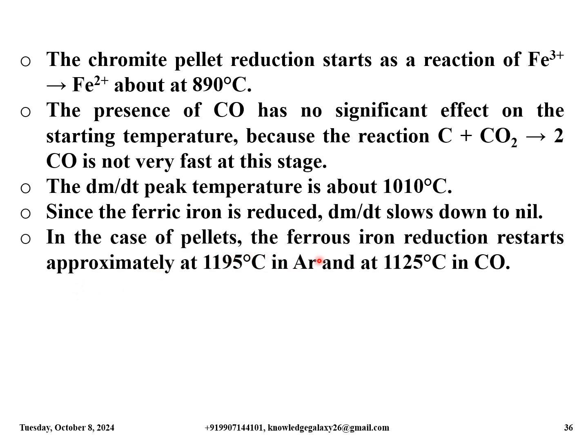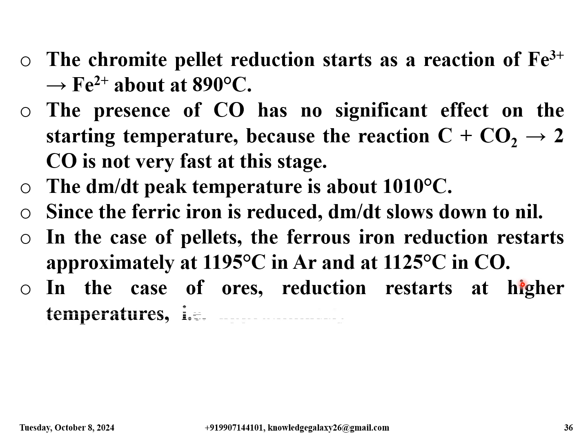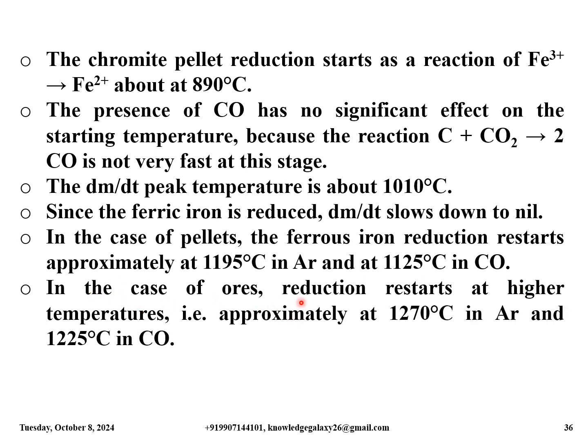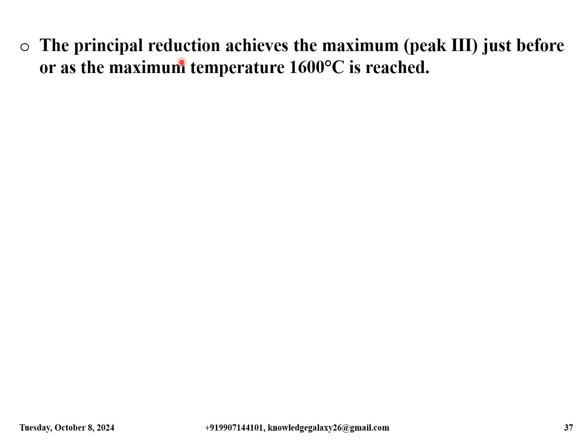In the case of pellets, the ferrous iron reduction restarts approximately at 1195 degrees Celsius in argon and at 1125 degrees Celsius in carbon monoxide. In the case of ores, reduction restarts at higher temperatures, approximately at 1270 degrees Celsius in argon and 1225 degrees Celsius in carbon monoxide. The principal reduction achieves the maximum peak, that is peak 3, which is shown in the next slide, just before or as the maximum temperature of 1600 degrees Celsius is reached.